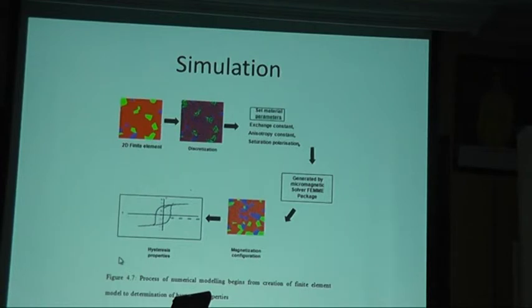Next is how I do the simulation, because we have the micromagnetic solver called FEMME. This one is 2D, previously it was 3D, so I just cut it into a slice and then do the discretization. In discretization, we divide the grain into small tetrahedra. If we design for 30 nanometer, which is quite big for a grain, I used to wait 3 months to get the results, because if we have a bigger grain, we have many tetrahedra.